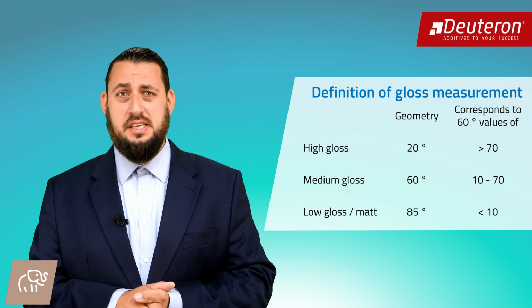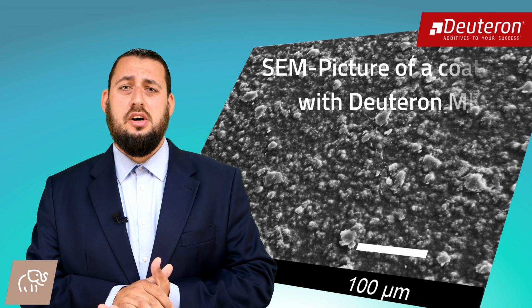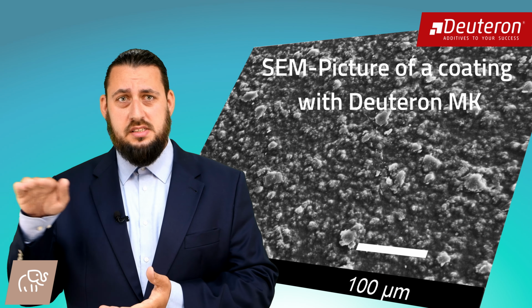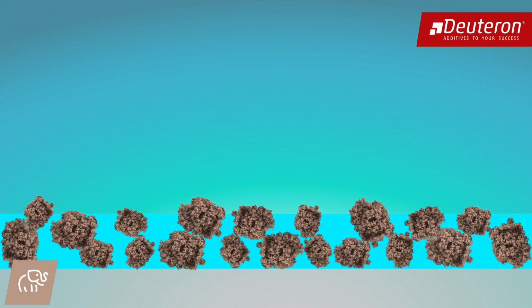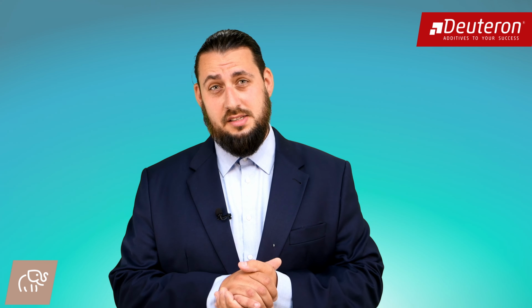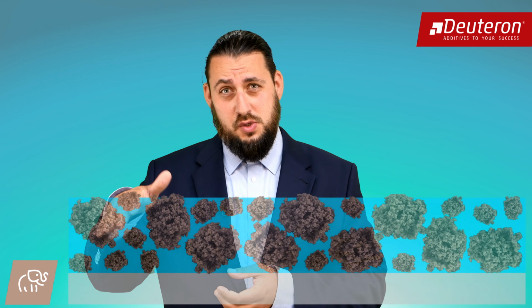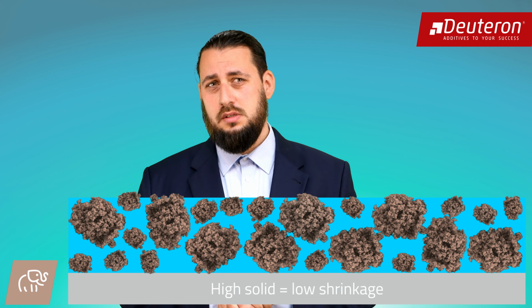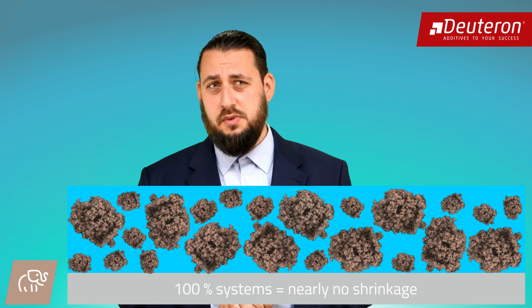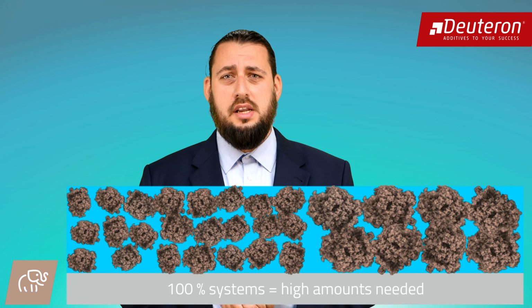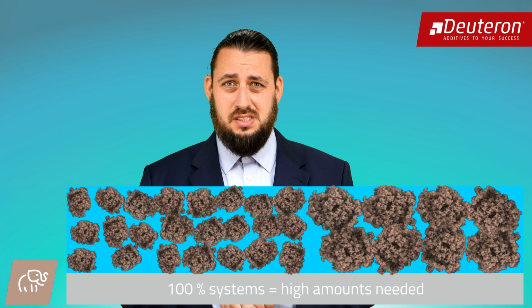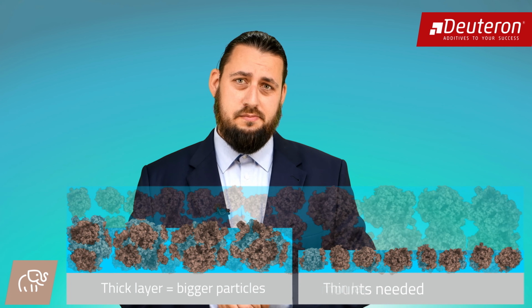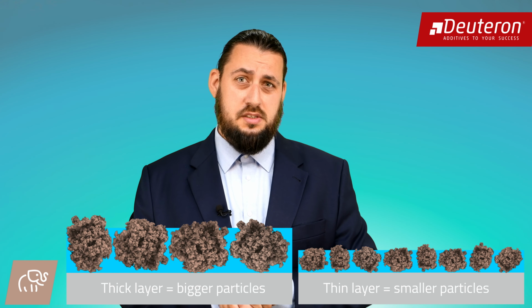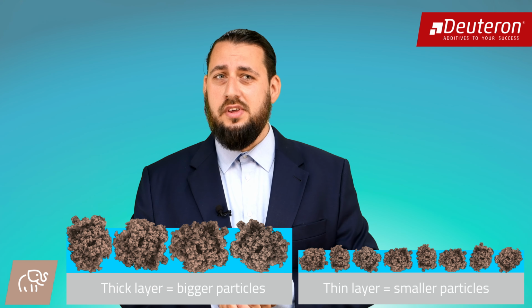The most important mechanism for matting is based on particles in the surface. The particles of the matting agents must be orientated on the surface. This happens usually by decreasing the volume of the coating layer during the drying process due to evaporating solvents or water. This process is often called shrinkage. If the volume shrinkage is low, the result is a low surface roughness. When the volatile content is low, matting is difficult, for example in high solid systems. 100% systems with nearly no volume shrinkage are difficult to matte. Too much matting agent would be needed and could lead to adverse effect on the viscosity. In principle, this is the case with every powder. One way is to use particle sizes in the range of the layer thickness. Thus, thin film applications can be matted very well, even if they are 100% formulations.